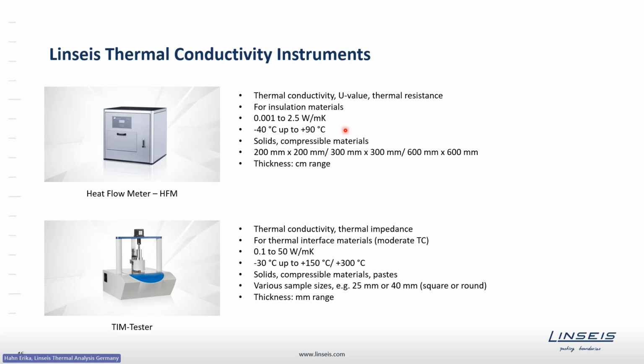Mainly the heat flow meter is used with solids or compressible materials like foams, for example. We need very large samples here in the centimeter range, 20 to 60 centimeters are needed, and also the thickness is more in the centimeter range. The TIM tester is measuring according to a similar principle. We determine the thermal conductivity of typically thermal interface materials with a moderate thermal conductivity. The temperature range is also quite limited, up to 150 or 300 degrees Celsius, but we can measure here a broad range of materials like solids, compressibles, or pastes, and the sample size is in the range of 25 to 40 millimeters, and thickness is mostly in the lower millimeter range.